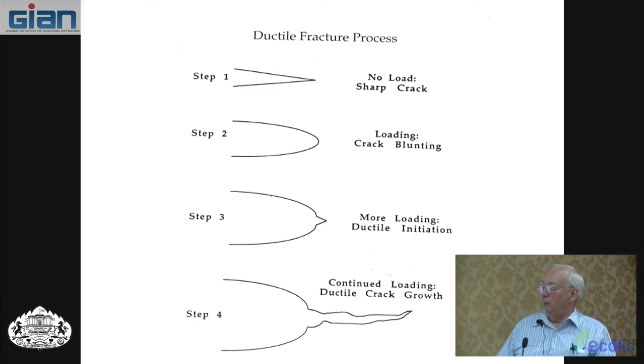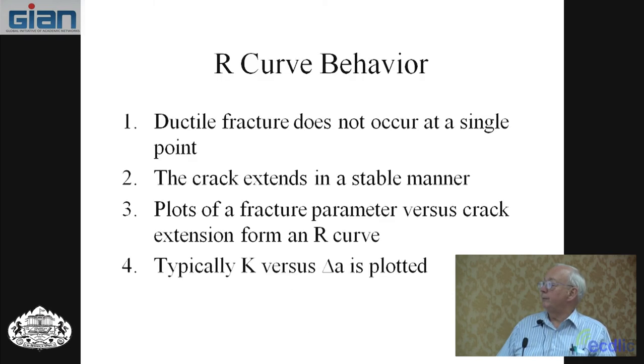And that again is built into the test methods. So R-curve behavior: fracture does not occur at a single point, but rather the crack extends in a stable manner. So people mostly plot a fracture parameter versus crack extension and form an R-curve. Typically for linear elastic fracture, you would use K as the fracture parameter. Delta A, the change in crack length, is plotted as the crack advance.